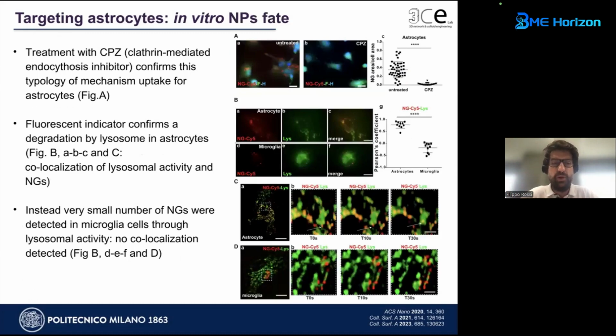We then treated with chlorpromazine, confirming the mechanism of uptake again of astrocyte, even if in this case it is clear, because as you know from the picture AC on the top right, using chlorpromazine, so inhibitor of endocytosis,